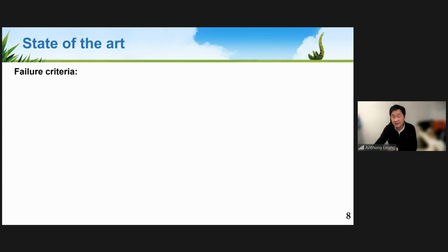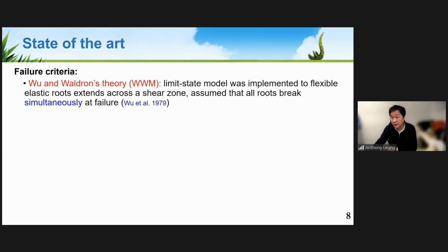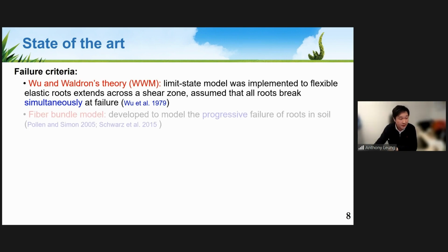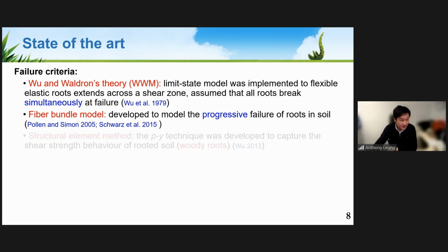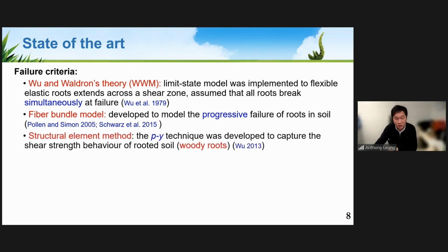So talking about the failure criteria, we have several models available to capture the root effect on reinforcement. One of the very famous models is the Wu and Waldron's theory, which assumes all the roots will break at the same time during the direct shearing mode. We do have also the fiber bundle model to improve the assumption for Wu's model by allowing the progressive failure of the roots rather than simultaneous failure of the roots. And if we allow for a more expensive numerical simulation, there are some finite element approaches using the p-y technique that could model the root-soil interaction for slope stabilization purposes.